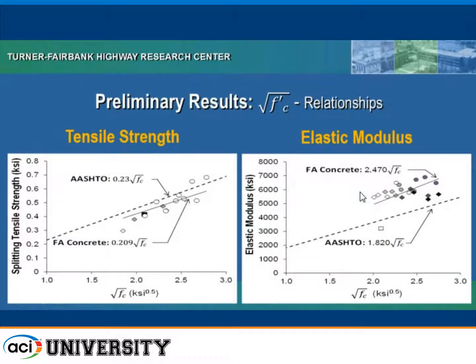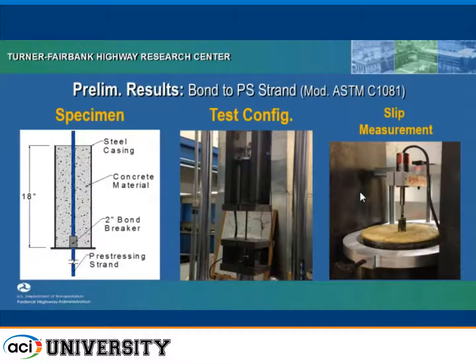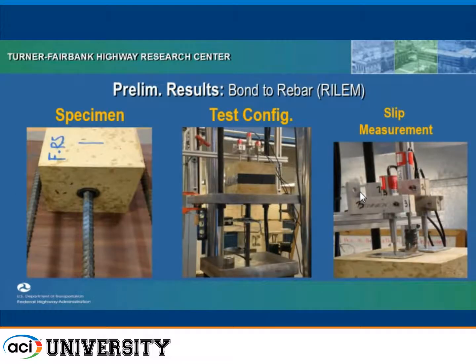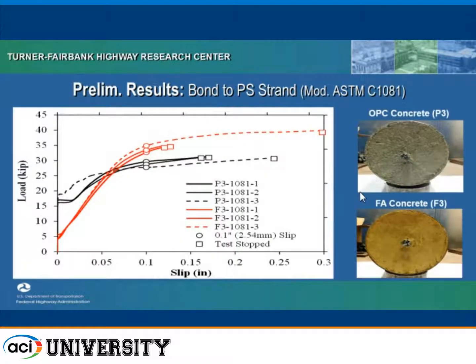This is just some preliminary results with the high fly ash concrete, where we took a look at splitting tensile strength in relation to compressive strength, and elastic modulus in relation to compressive strength. We also did some initial pull-out bond to prestress strand tests using a modified ASTM C1081 test, and preliminary results on a RILEM test on bond to rebar. And this just shows some of the preliminary test results. Unfortunately, we have just begun to get involved in this and get a little data, but have not been able to continue it at the present time.